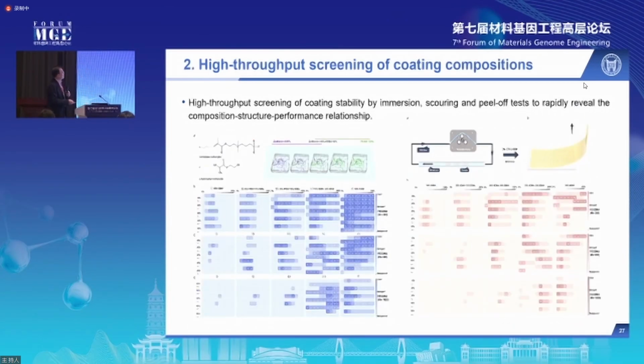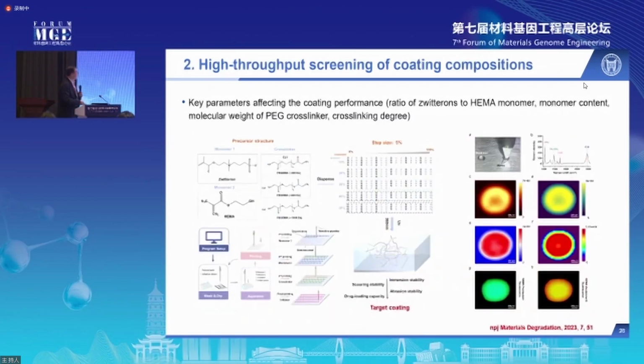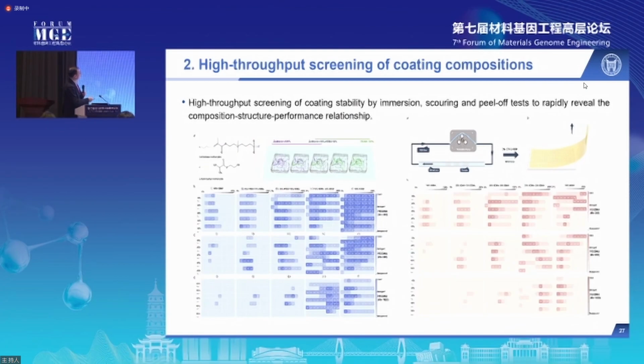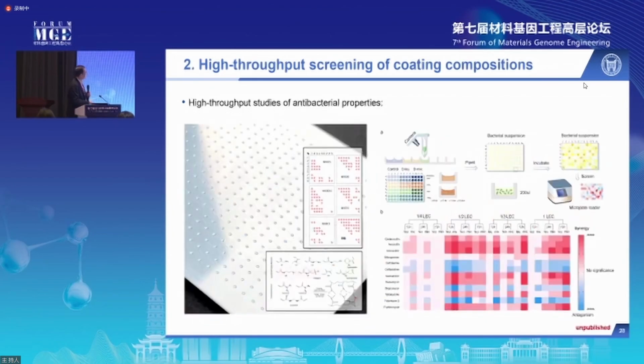And once we have these arrays of coating dots, we can immerse them for swelling, and we can do peel-off tests, nano indentation, and contact angle, and do a lot of tests to quickly understand the composition-structure-performance relationship. And this is for antibacterial surface analysis, using a similar fashion.